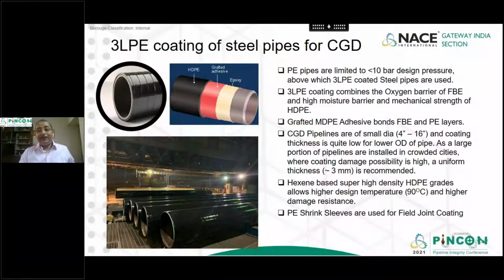Now coming to 3-layer PE coating of steel pipes for city gas distribution. PE pipes are limited to less than 10 bar design pressure, above which you have to use steel pipes with 3LPE coating for corrosion protection. Now 3-layer PE coating combines the oxygen barrier of epoxy and high moisture barrier and mechanical strength of HDPE. Therefore, they are better than individual FBE coating or polyethylene coating. And since polyethylene and FBE do not bond to each other, grafted MDPE adhesive is used for bonding them.